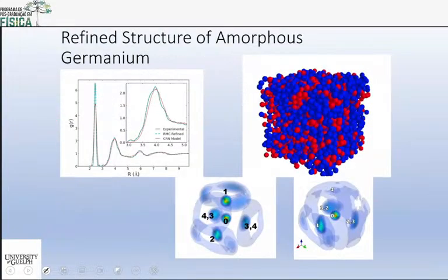So this is an interesting thing, for you computational people out there. What we did was we came up with a box. Computationally, we put 100,000 atoms in a box. And what we did was we put them randomly and moved the atoms around, calculated the diffraction pattern that you would get from this random arrangement, and compared it to the measured pair correlation function. And we just kept on moving atoms around and accepting moves that made the fit better. And we just kept on doing it.